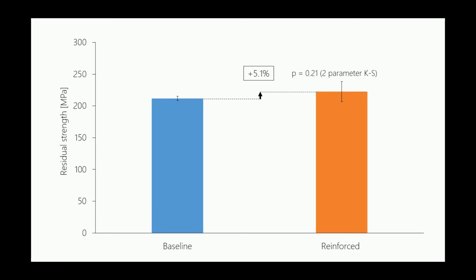Given the improvement in delamination area and mode 1 fracture toughness, the lack of improvement of compression after impact strength is somewhat unexpected. However, this lack of improvement can be explained by the following hypothesis. This image shows the photograph of the back face of a specimen after it was impacted. We see clearly signs of fiber damage, and if we zoom in, we can even find evidence of damage to